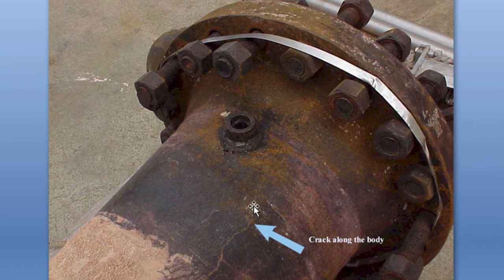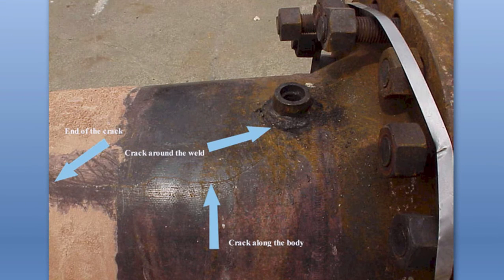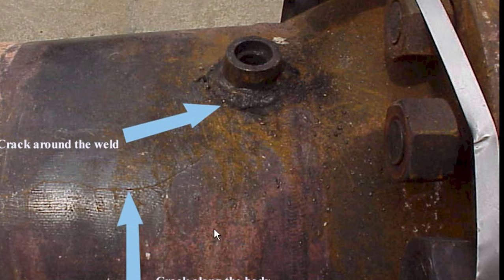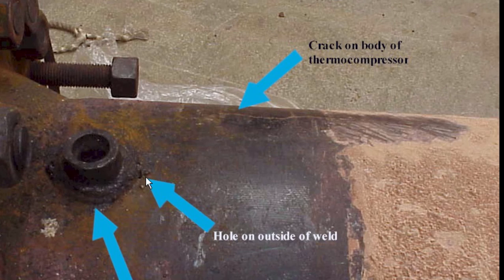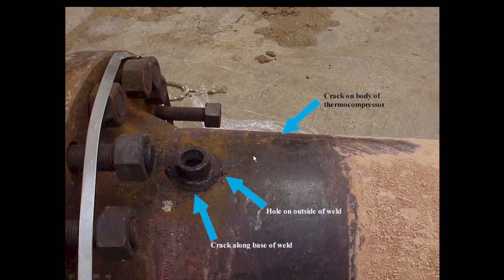And of course, we're looking at how the crack propagates into the base material. But when we get over here and we start looking at this, let's make this a little bigger. If you notice the weld pattern, also notice the coloration, going from a straw color to a deep purple or black color. Now this tells me, and I'm going to end up proving it, that this was either welded with too much heat or it was welded wet, which I sincerely doubt. There's the hole I was talking about.